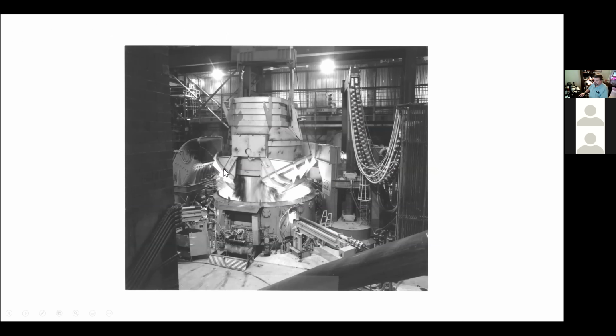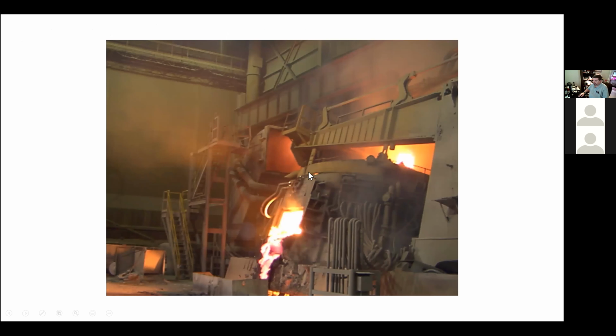So here you see the scrap. You see the clamshell swinging up to the sides, which allows the scrap to fall down into the furnace. And then we swing the roof back over and we melt. So once we're done melting, we take a test through what is called the slag door at the back here. That allows us to tilt back and pour off some of the slag if we desire.